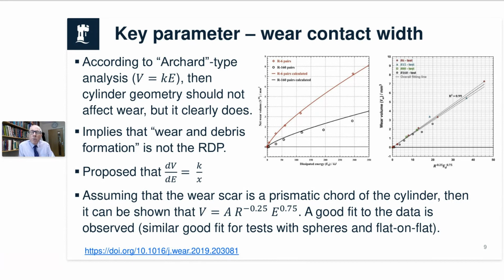And in fact, the data that we've presented here in the middle diagram, that's with a 160mm cylinder and a 6mm cylinder. They're very different. But what we proposed, based on some earlier work from the 1980s, was that the wear rate, dV by dE, was proportional to 1 upon the wear scar size.